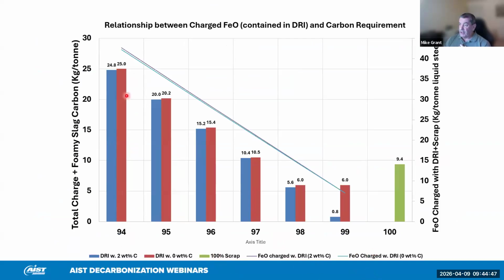So I've calculated the amount of carbon that needs to be charged in each case, depending on the metallization. And you see with 94 percent metallization, we need about 25 kilograms of carbon per ton of steel just to control the FeO in the slag, reduce that FeO back to iron so that we can recover that metal. And of course, these are emissions. And as we increase the quality of the DRI, we approach 99% metallization. The amount of carbon that we need to inject comes down a lot because we need to reduce a lot less FeO.